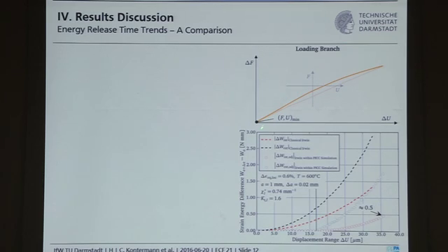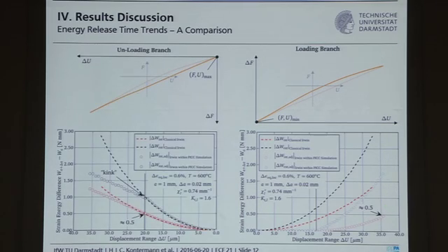That's very clear because the crack is closed here up to a certain displacement range. So the energy difference has to be 0. And then the strain energy density will rise up to an end value of 0.5. The interesting thing is now we can do this evaluation not only for the loading branch, but also for the unloading branch. So if we look at these results, we see here the unloading branch going from maximum to minimum now. So 0 means maximum loading.